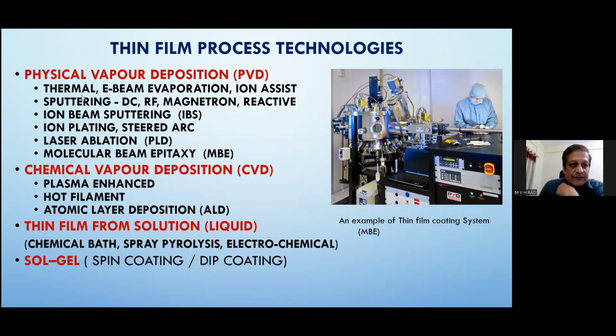These first two have been there for almost 30 years. Later, the ion beam sputtering method has come up. In this case, instead of giving energy internally or improving the number of ions, they thought they would give argon ions sufficient energy to bombard directly. So argon ions are ionized and accelerated with high energy, and those accelerated argons bombard the surface. Then the target is etched out by sputtering. The word sputtering, used very often, is nothing but knocking off atoms by argon ion or inert gas ion bombardment. It is basically a momentum transfer process. So that is physical sputtering.